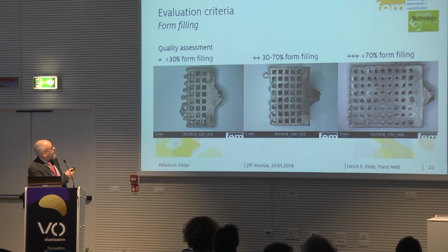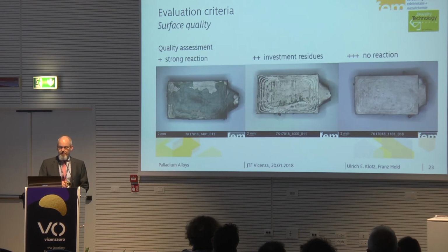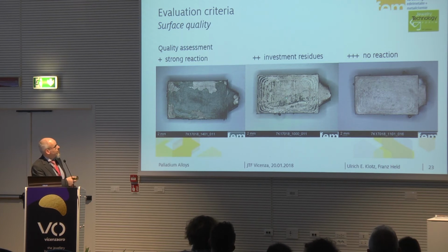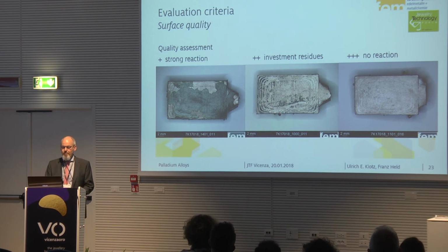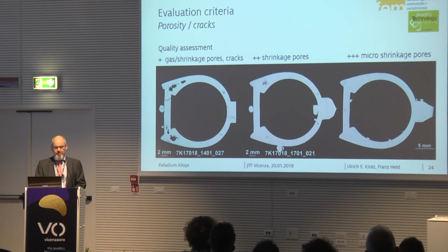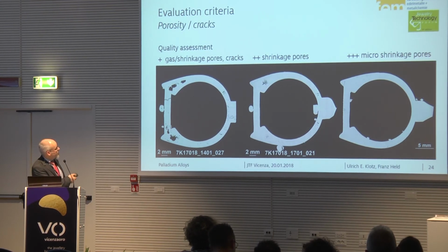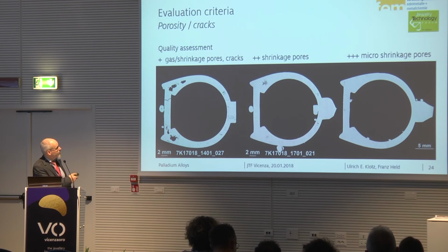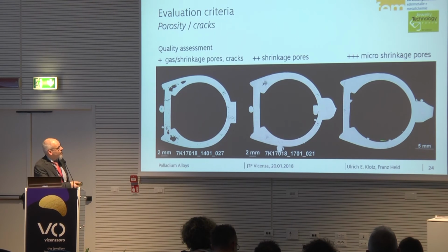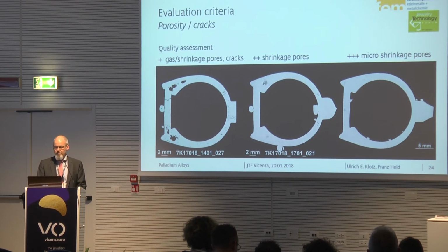We assessed typical parameters like low form filling, medium, and high form filling. Similar for the surface reaction: strong reaction, some residues of investment, and no reaction. And the same with porosity and cracks. Of course, this is useless quality with cracks and many pores. Here we have some porosity, and this one is more or less free of pores.